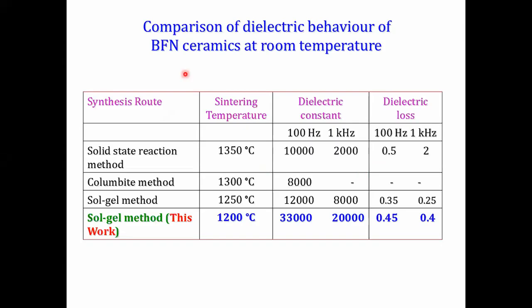Now comparing this material's dielectric properties with other reported things in the literature - people have made the same material BFN by solid state reaction heated at 1350, and they got around 10,000 with a certain dielectric loss. Some people made it by the Columbite method, other people have made it by sol gel method at 1250, but we made it at 1200, and we got a very high dielectric constant of 33,000 at 100 Hertz, and at 1 kilohertz it is around 20,000, with loss almost comparable. So our work has much better value than the reported values.